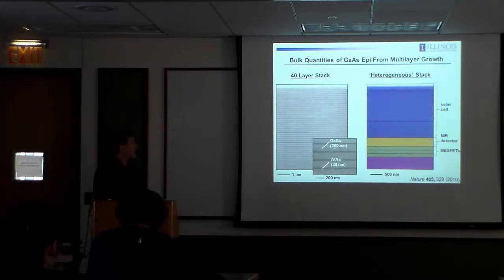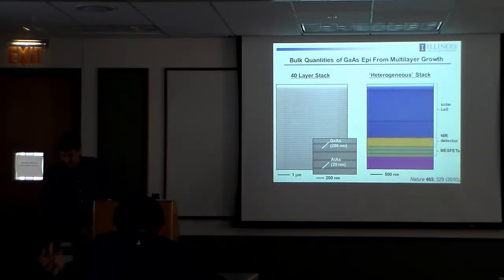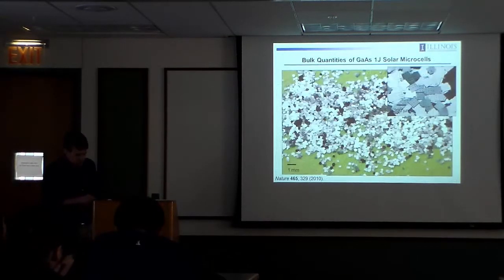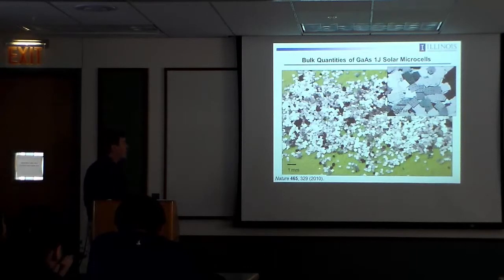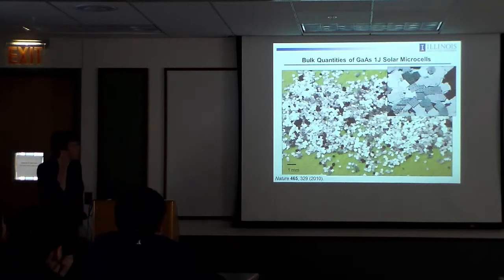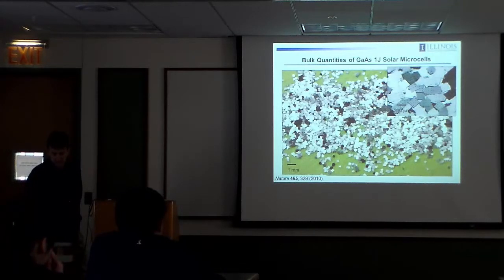And you can do this in heterogeneous stacks also. These are just uniform layers of gallium arsenide. You can change the doping constructs to create solar cells, sacrificially separated from, let's see, near infrared detectors, MESFETs. You can do sort of heterogeneous collections of materials for different classes of devices the same way. And this is what it looks like if you lift it off and then deposit it down onto filter paper. So you can do this in large quantities in strategies that are fully aligned with mainstream industrial approaches for growing materials and implementing them in devices.